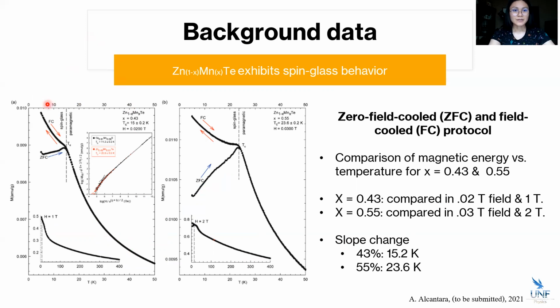So this is experimental data. This is a known diluted magnetic semiconductor, zinc manganese telluride, doped with the manganese at 43% and 55%, replacing the zinc. You can see here that the system is cooling, and it follows this paramagnetic behavior. This is very similar to what our fridge magnets do. They all face one particular direction in their spins and attach to the fridge magnet. But the difference between a paramagnet and a spin glass is that as soon as the applied field is removed, the paramagnet goes right back to normal, whereas a spin glass, if it's induced by a certain transition temperature, would actually measure remnant magnetization, so it locks onto its spins, creating a glass-like structure.